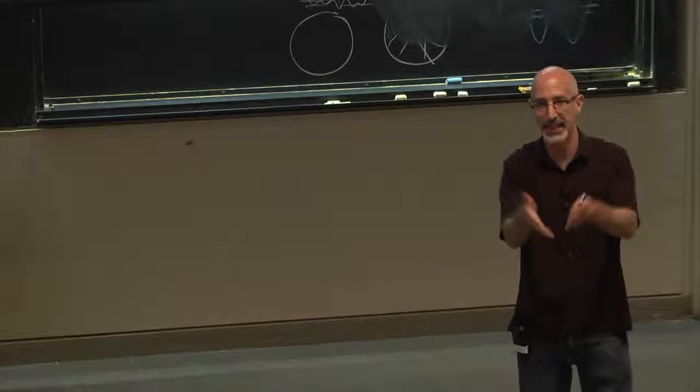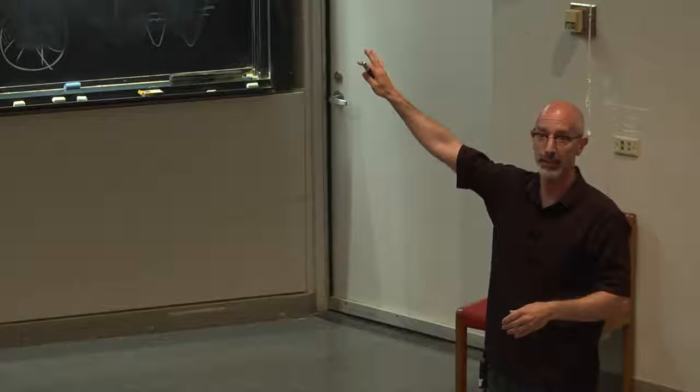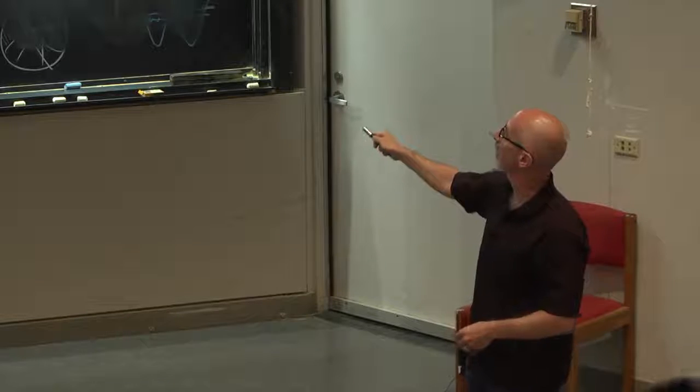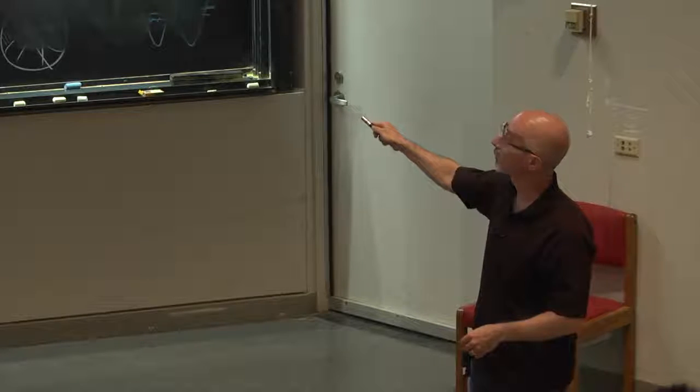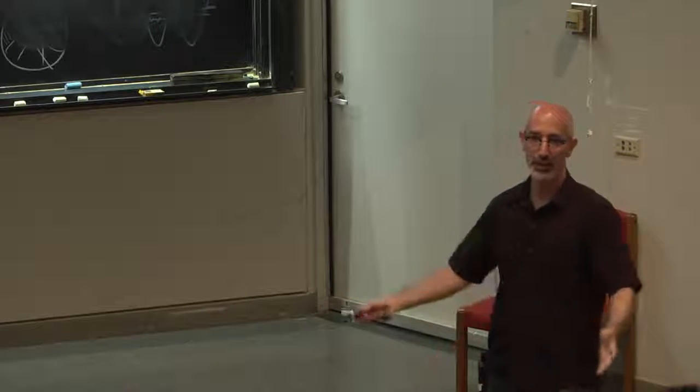So it's not that you can't see the length scale. It's not that finite size effects are so strong, although in some systems people claim they are. In these systems the length scales really are small-ish, and certainly you don't see large finite size effects in the dynamics at 1,000 particles. But to do an extrapolation, you'll get different answers depending on what scaling form you use. Whether I take this to be purely Ornstein-Zernike, or I make it 1 plus the length scale times q to a power that's not 2, will change the answer.